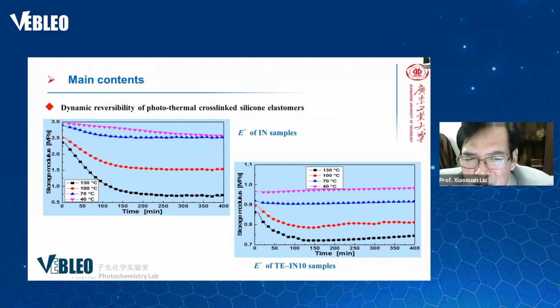Dynamic reversible photo cross-linking silicones. This is the storage modulus changing with the samples, and this is different for the samples. One is the IN samples, IN networks, and the TE-IN chain. The IN network contains 10% samples. This is the different stress.